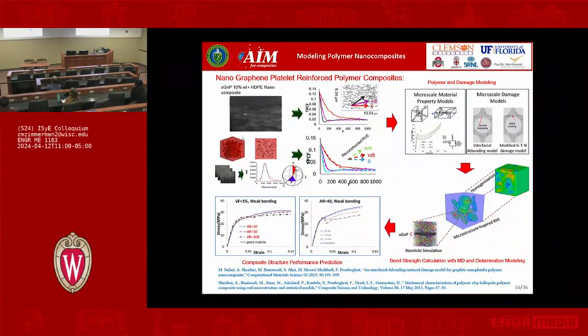So to create from these type of statistical data, we go through an iterative process of generating these representations. We use a code that is called Dream 3D. That thing goes through thousands of iterations, and it puts these different platelets, or you can put different kinds of spherical or whatever you want in there. It creates these things, and then it checks the properties of them, as if it does a 2-point correlation test on it, or it looks at the distribution, until we get the same match with respect to the size. That's a reconstructive process that's very tedious. But once it's done, now we have a geometrically identical property, statistically the same as before, right?